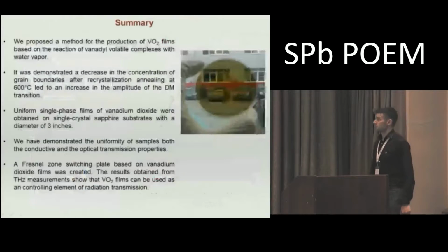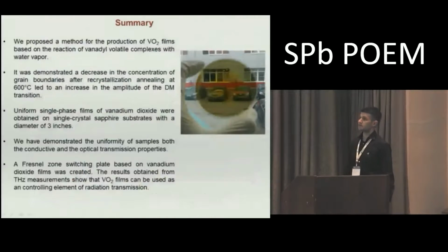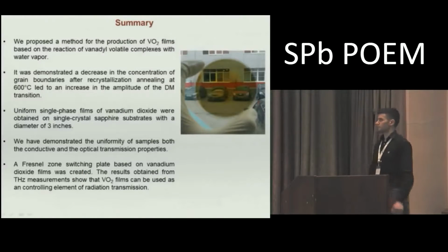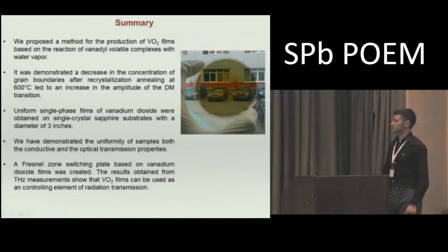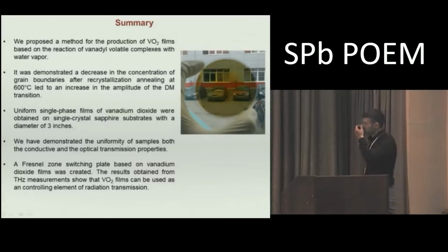So that's all. This is my summary. We propose a method of producing vanadium dioxide films. We show that we got uniform single-phase films of vanadium dioxide, that the electrophysical properties are also uniform, and there is no dependence on the radius of our samples.